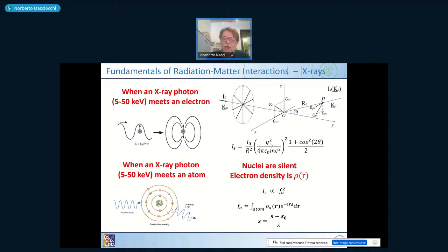q is the electronic charge. m is the rest mass. c squared is the square of the light velocity. So this number is a fixed number. It's a very small number indeed. That means that the scattering intensity is much smaller than the incoming intensity, because there is this term which is below 1, r squared is certainly larger, and also this term is very small. One thing to notice is that if you have no charges, so if a particle is not charged, if you have a neutron here, then the intensity is automatically 0.